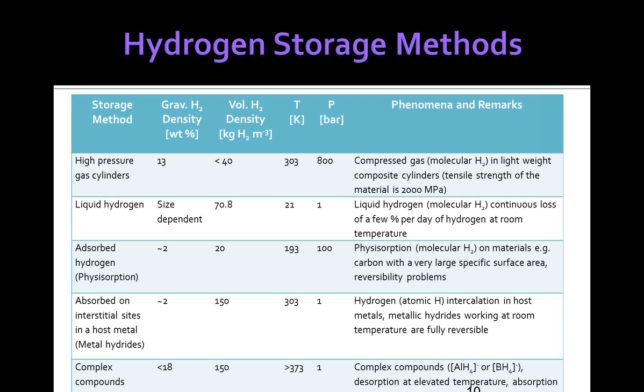The third one is adsorbing the hydrogen. That's called physisorption. Physisorption means you can take the hydrogen molecule or atom and adsorb it onto the surface of the material. Then the gravimetric capacity is about 2 and volumetric is about 20. That's much higher. The temperature, we are still working with 193 Kelvin and pressure is about 100 bars. So much improvement has come on this subject.